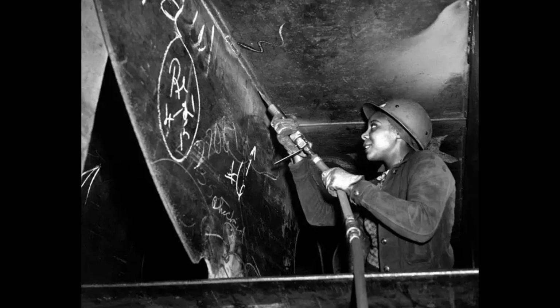The steel itself is the problem, not the welds. The steel used in Liberty ship hulls suffers from a property called ductile brittle transition. At normal temperatures, the steel is ductile. It can deform, absorb energy, resist crack propagation. Below a critical transition temperature, the same steel becomes brittle. It cannot deform. Cracks propagate explosively with minimal energy input.